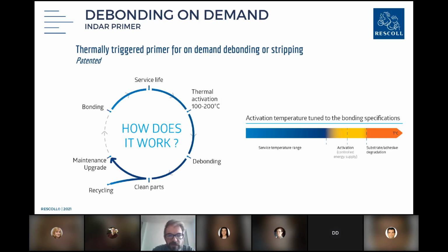and then you have the service life, which is unaltered, very similar to what we would have without the technology. And then once you want to do the debonding or stripping, you have to thermally activate in the range of 100 to 200 degrees C. Of course, the activation temperature is tuned to the bonding or coating specifications, mainly with no degradation on the substrate, which is what we target for further processing, recycling, or reuse. And then after the triggering, you can separate the coating or the parts. In case of bonding, you clean the parts very easily, and then you can do the maintenance, or upgrade, or recycling.